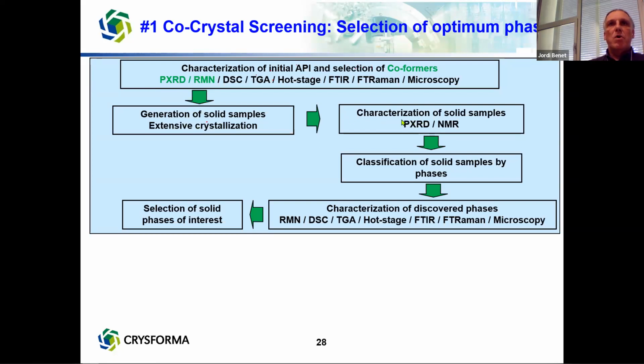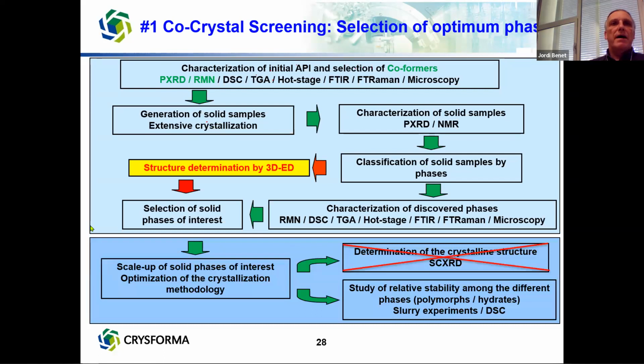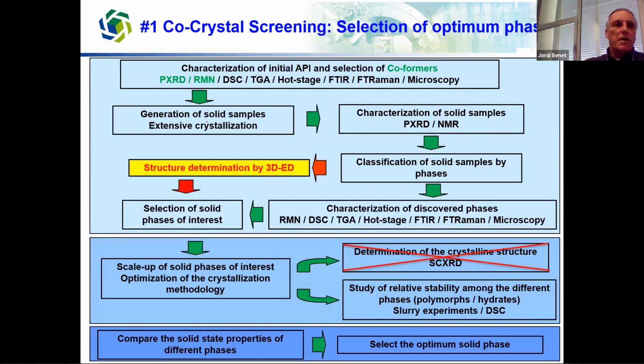Then we characterize them by powder diffraction and NMR and try to make a selection or classification of them. If we have different phases, we characterize them more properly, and finally we go to a final solid selection. Then we would do a scale-up and a final characterization with single crystal, which implies that we need to crystallize and get single crystals. But now the big change is that we can erase this point and go directly, when we do the classification, to 3D-ED and get much more information on our solids. So this was the end of the process where we try to get the optimum solid.